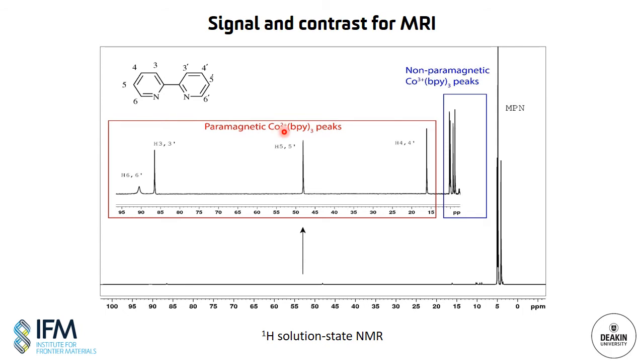Now, while these paramagnetic shifts for these protons opens the possibility of shift-selective imaging to observe the paramagnetic species, they do, as you can see, have very small intensities, and obviously they also have very short relaxation times, so they're not really amenable to MRI. So what we're doing to record our images is actually focusing on this MPN signal. And this allows us to probe the paramagnetic species indirectly.